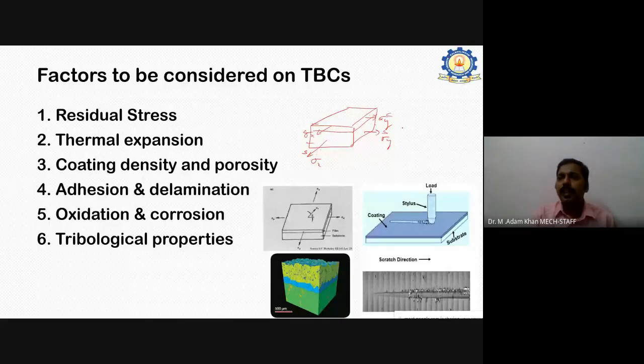For example, if I want to check the strain for any bulk material, I can say stress divided by Young's modulus. If I want to see the differences, I cannot equate the strains, but I can equate in terms of stresses. The stress induced here and here will not vary, but the strain induced in this and this are different. So when you are talking about the residual stress, you should be very careful to note whether we know the stress of the coating or the stress of the substrate. If it is known, you just subtract it. Sigma 1S minus sigma 2, sorry, sigma 1C, in terms of Young's modulus E over one minus Poisson's ratio, into strain. This will be different for coatings and for the substrate.